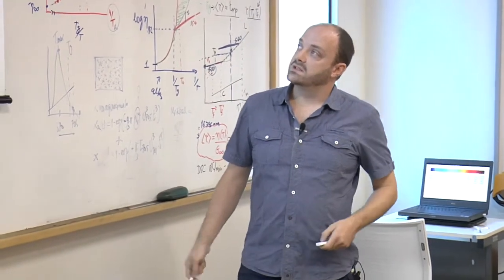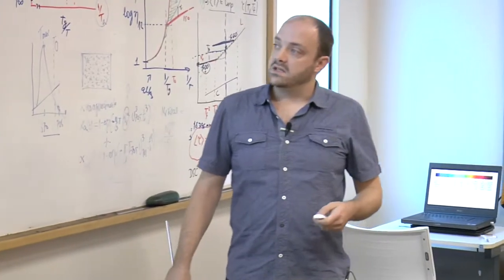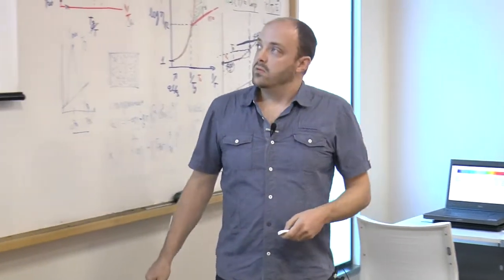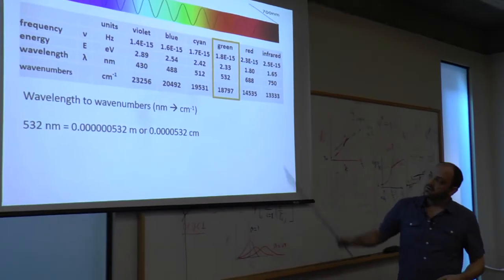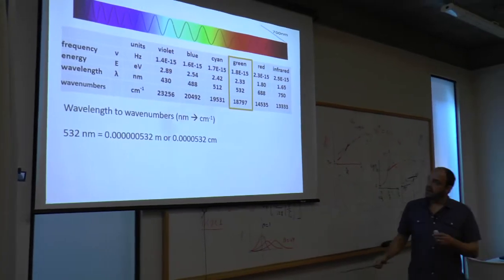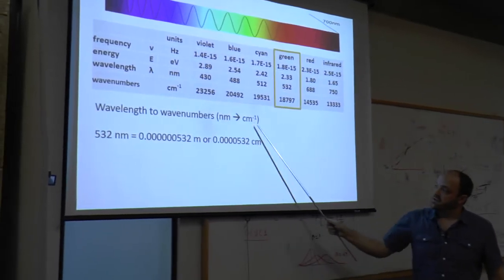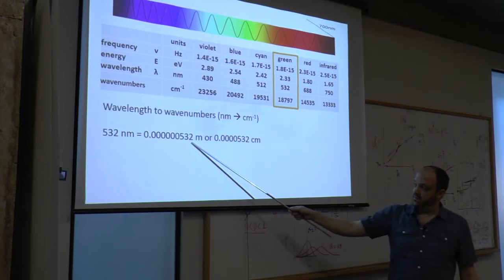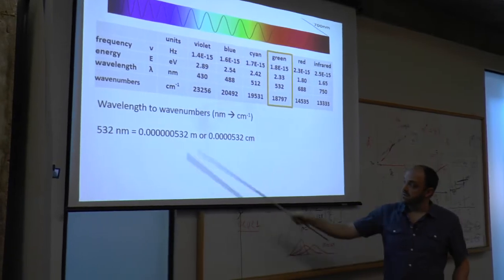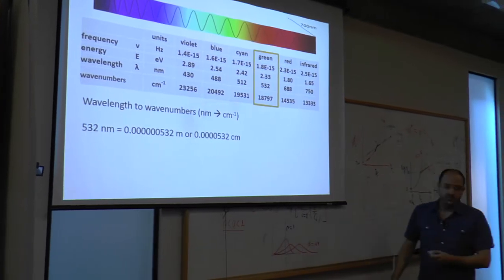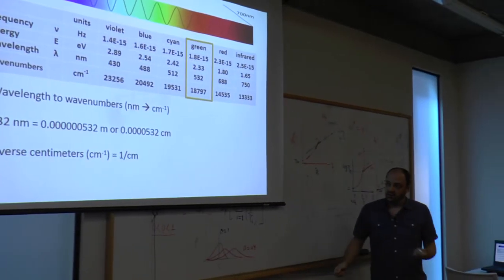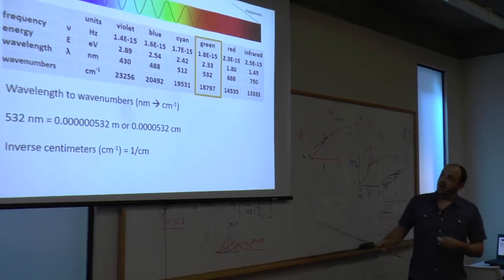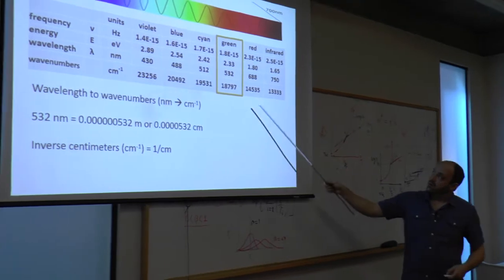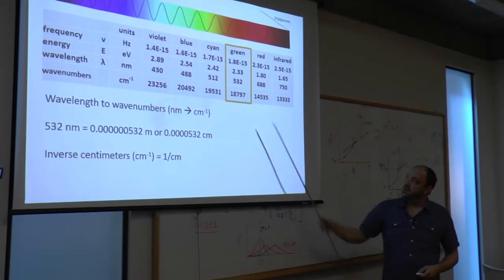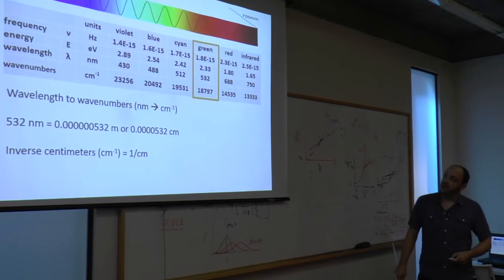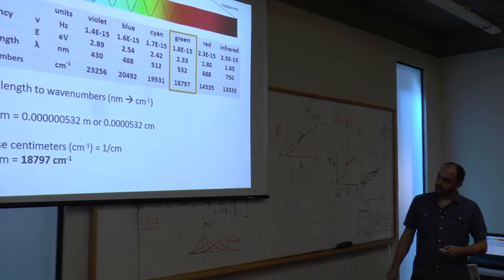So just to go through a quick example of the green wavelength, because this is something that sometimes trips people up. We can go from the wavelength to inverse centimeters in a direct way. When you move from nanometers to centimeters, this number of nanometers is equal to this many meters. It's equal to that many centimeters. Very simple, straightforward conversion. And all you do is take the inverse of that to get wave numbers. So the wave number for a green laser is 18,797 inverse centimeters.